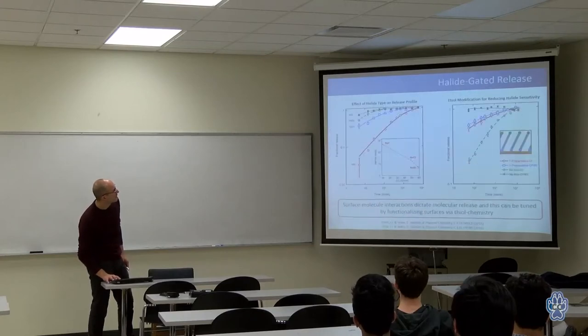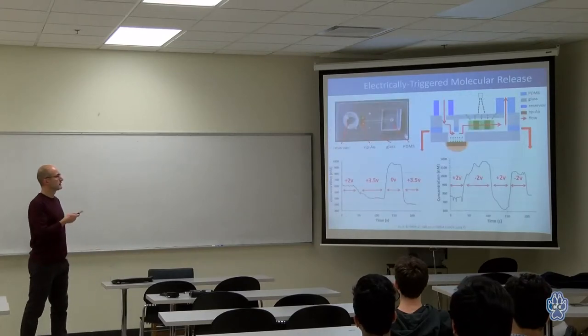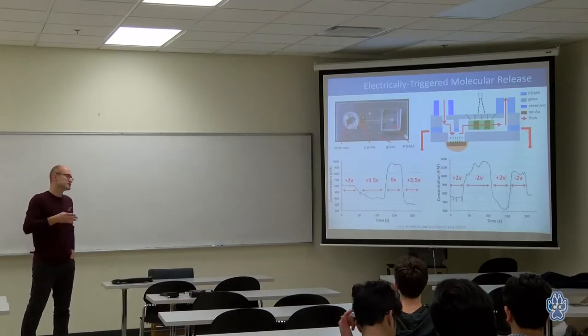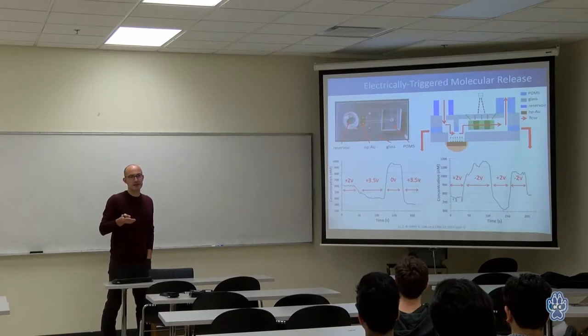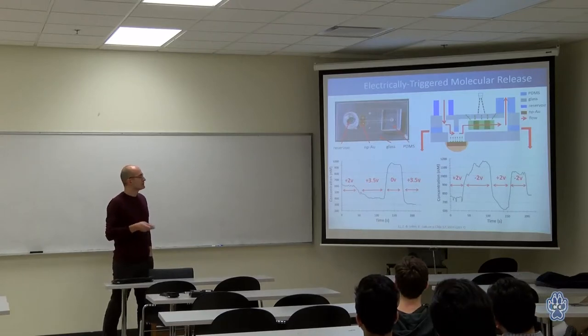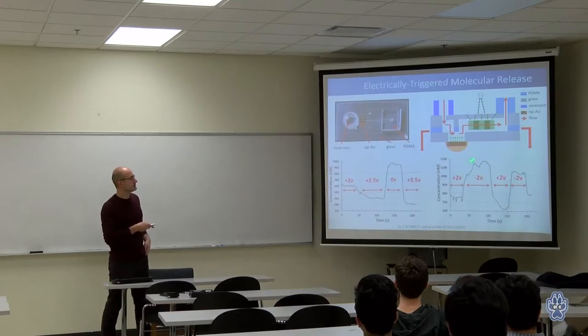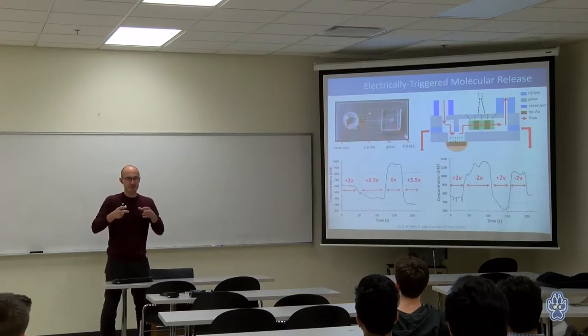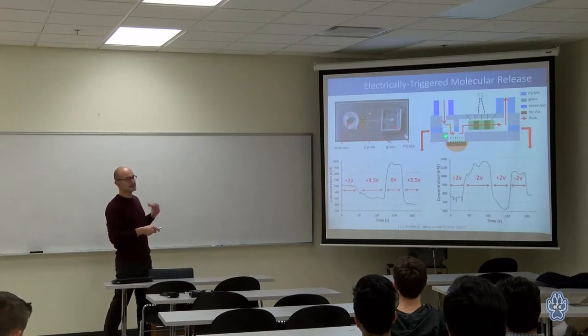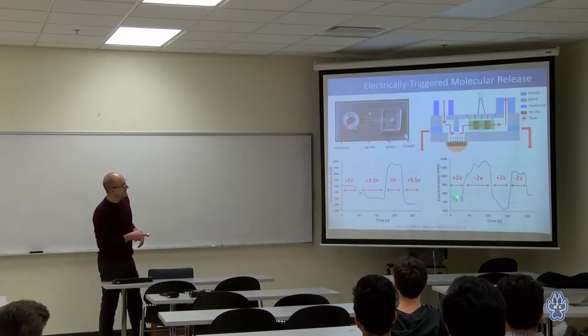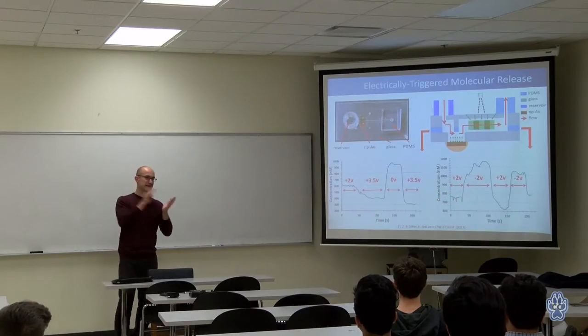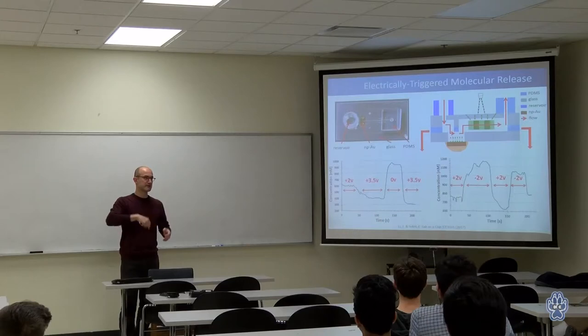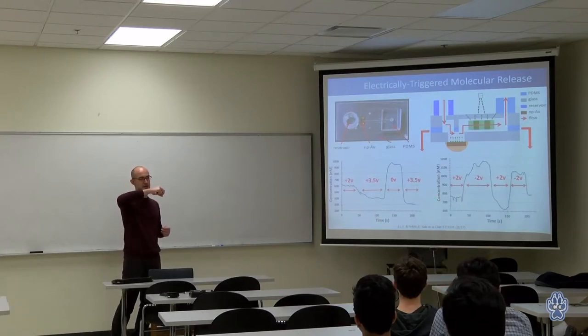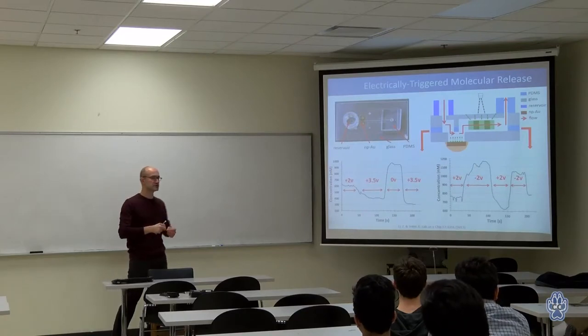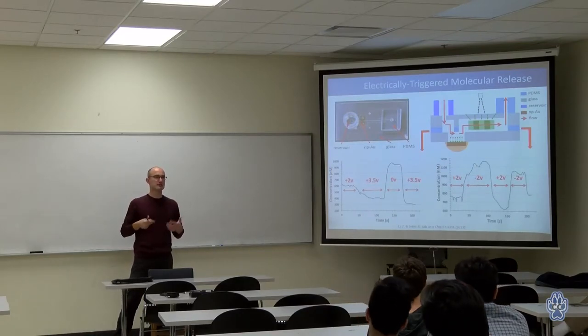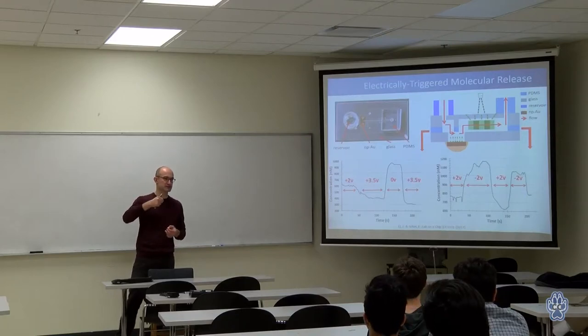I'll give one example of this. You can change the surface properties by adding chemical moieties, but you can also change the surface charge. Remember, nanoporous gold sponge is electrically conductive. So if you have a drug molecule that is negatively charged in that porous structure and you apply a positive potential, the drug molecules would electrostatically attach to the wall and stay there. But if you apply a negative potential, you can push those drug molecules out. So now you can create arbitrary waveforms of the drug molecules. You can do dosing on the order of picoliters of drug molecules that you can release.